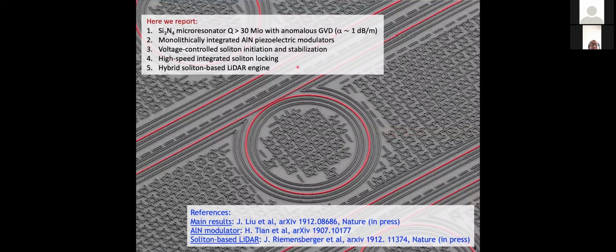In this talk, I will show a silicon nitride microresonator of Q more than 30 million with anomalous group velocity dispersion. This corresponds to a linear propagation loss of 1 dB per meter due to our optimized Photonic Damascene process. And then I will show the monolithically integrated aluminum nitride piezoelectric modulators on silicon nitride photonic circuits. By changing the voltage, we are able to control the soliton initiation and realize soliton stabilization. Also, we can do high-speed integrated soliton locking. Then we use this new capability to demonstrate a hybrid soliton-based massively parallel LIDAR engine.